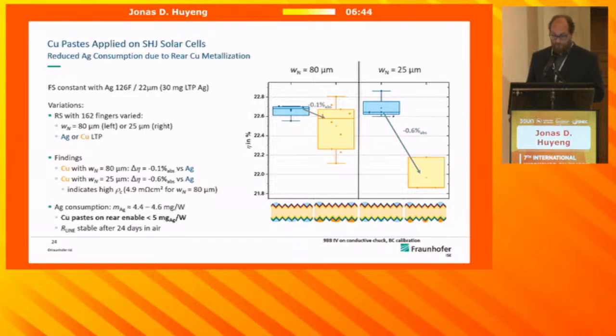The good news, of course, while there's still room for optimization, is that the silver consumption, considering fully rear-side copper metallization, is already in the target range that we want to go to. So depending on what efficiency you're reaching, of course, the numbers change a little bit because you're changing the denominator, but you're already below 5 milligrams per watt. And then, of course, the next question is, what about the reliability? So these are some quite fresh results. We haven't been able to do all the long-term testing, but at least the line resistivity that we've been monitoring for about a month now has been quite stable.